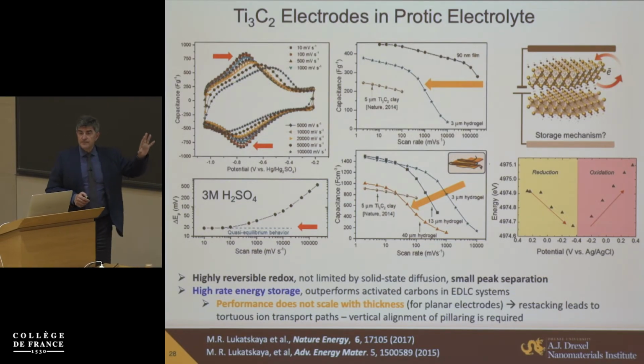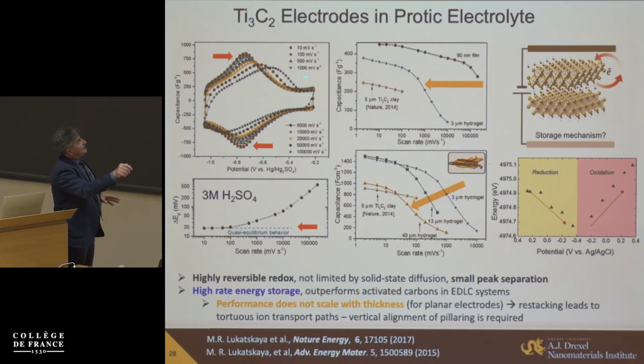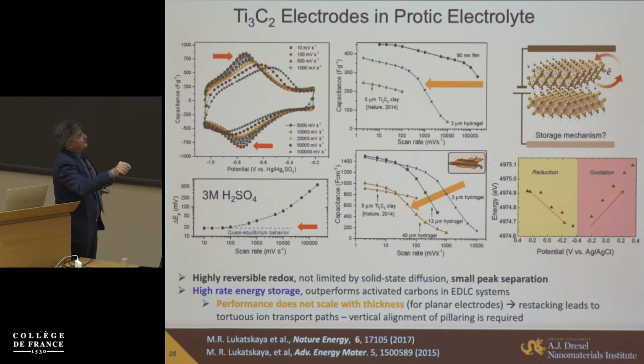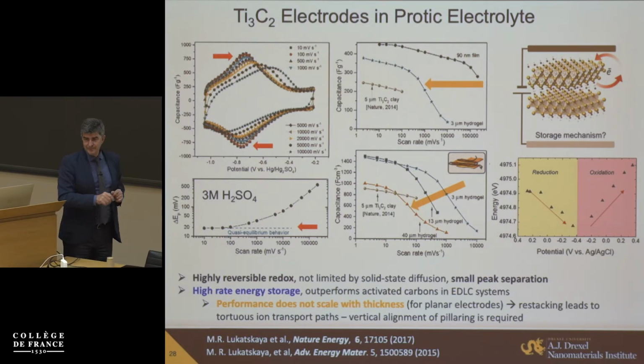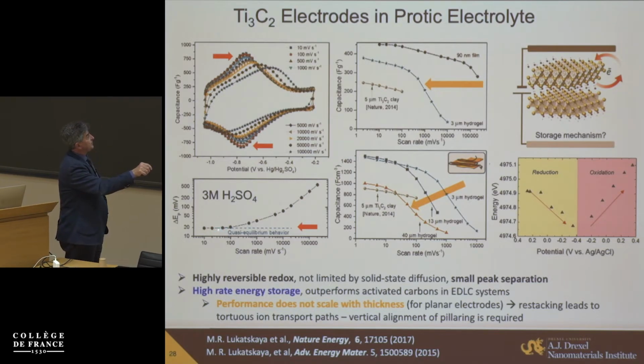What you see here are typical cyclic voltammograms for titanium carbide Ti3C2 MXene, with oxygen and OH usually on the surface primarily, in sulfuric acid electrolyte. What is interesting? If you are at a relatively slow scan rate, millivolts per second, 200 millivolts per second. For batteries, most of what you do is a very high rate already. But this is typical supercapacitor operation rate. You see, there is a capacitive envelope. Here it almost doesn't change up to 100 volts per second. And there is this peak. And this peak is completely electrochemically reversible.